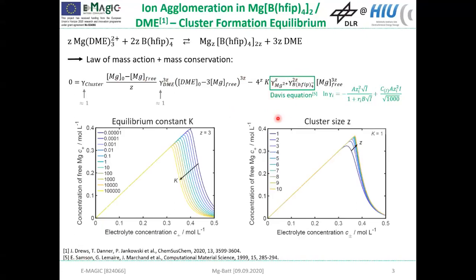Since the exact properties of the clusters are not known yet, we looked at the influence of the equilibrium constant K and the cluster size Z on this equilibrium. And in general, we see that there is a critical concentration, which you can see here as a maximum in this graph, at which this cluster formation takes place.